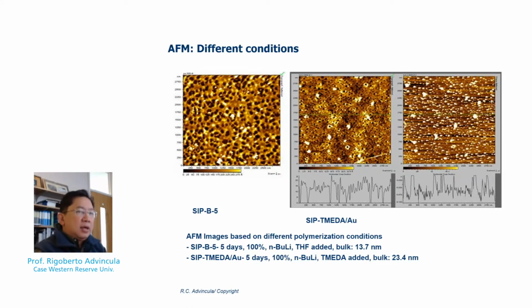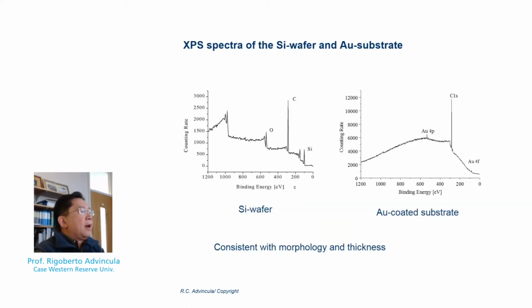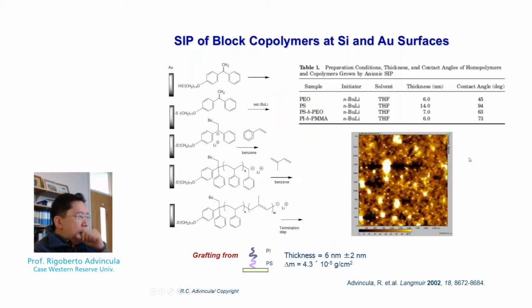And here we use, for example, X-ray photoelectron spectroscopy to verify the presence of grafted polymer, in this case polystyrene, on a silicon wafer. So you can see the silicon and oxygen peaks on the binding energy associated with these elements. And on the right, we have a gold-coated substrate, which verified again the grafting of the polystyrene on a gold wafer surface. So moving to block polymer strategies, as I mentioned, we were able to graft polystyrene and then followed by a grafting of isoprene.